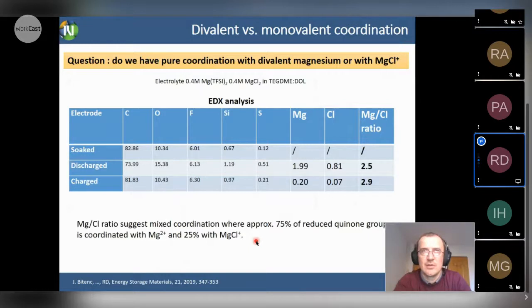That's fine once you are working in laboratory cells with a huge excess of electrolyte, but once you are moving close to commercialization, then each drop of electrolyte counts on energy densities. That means each microliter of electrolyte that is added is important, but this also gives us depletion of electrolyte with chlorides, and so we are still working to find the best combination between magnesium and chloride and TFSI salt, which can give us the best capacity.